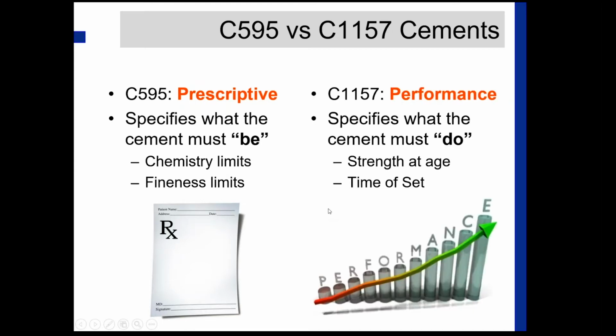But when you look at C1157, again, it's a performance specification, so that specifies what the cement must do. In other words, we don't care how it's made necessarily. We don't care what you had to do to make this powder to get it to do whatever it does. We just want to make sure that it reaches maybe a certain strength at a given age or a time of set in a certain time frame, whatever it might be. So it kind of frees up the producer to make a powder that's going to meet a certain performance criteria, not so much follow a cookbook recipe.